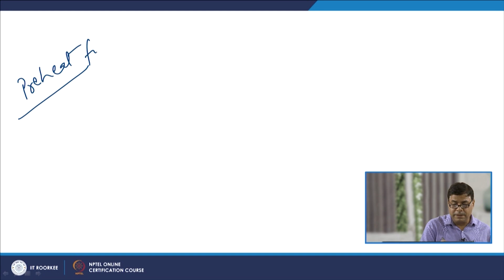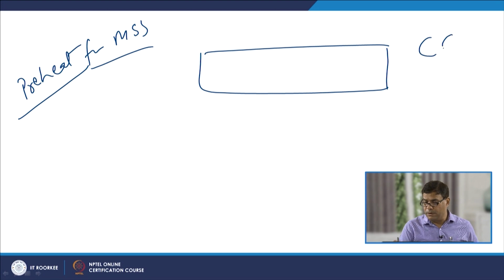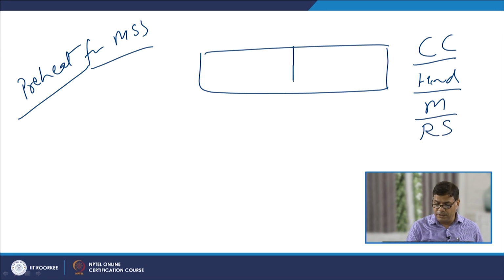Apart from this, there are other aspects like the kind of preheat we need to use for welding of the martensitic stainless steel. We have seen that this kind of steel is sensitive to cold cracking because of the high hardness, martensite formation and development of residual stress. So, in order to reduce the cold cracking tendency and especially the reduction in toughness of the heat affected zone, it is important to use the appropriate preheat so that the cold cracking tendency can be reduced and enough opportunity for escaping of the hydrogen can be provided.